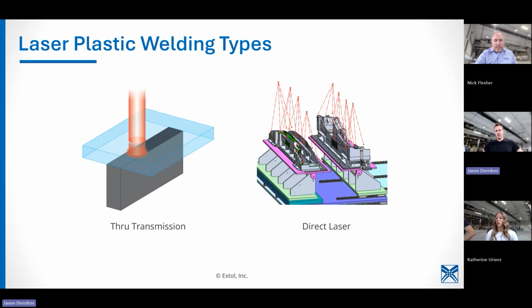Great question, Max. Another good question. Are direct laser welds as strong as the transmissive? Not so much, actually. We can get 80%, 90% laser parent material strength through transmission. Direct laser, you do see some reduction. So we typically will recommend, if your wall thickness, I'm just making up numbers, is 2 millimeters thick, a 6 millimeter or 5 millimeter weld thickness. So you can still get the strength. You're just having to weld more surface area to do that.